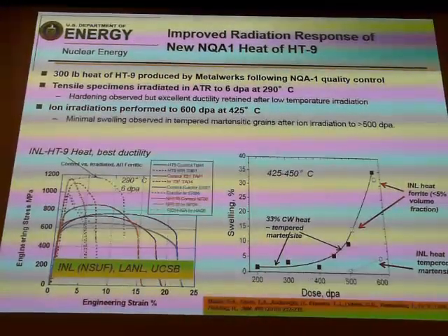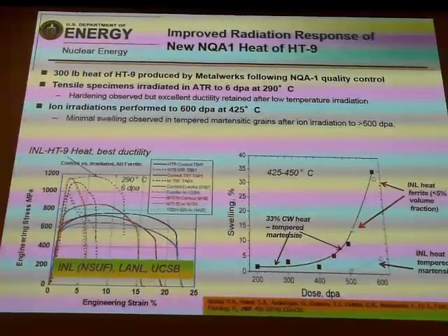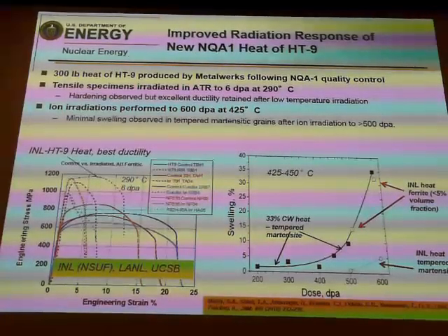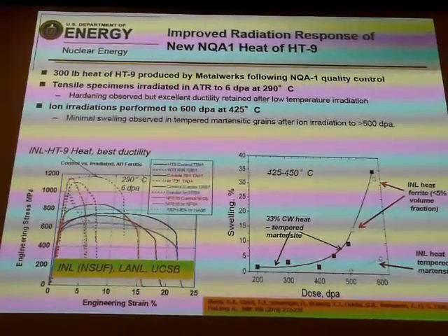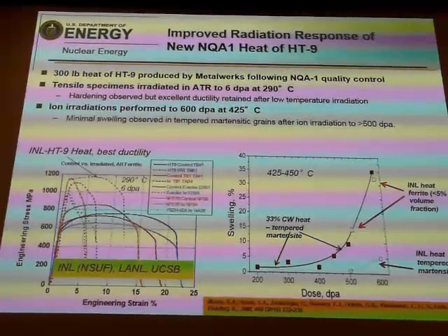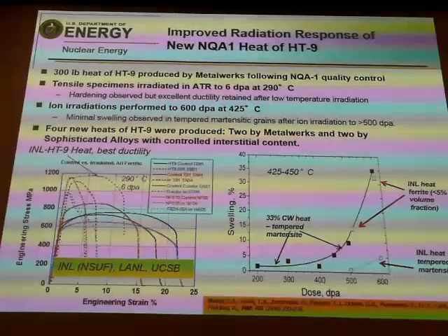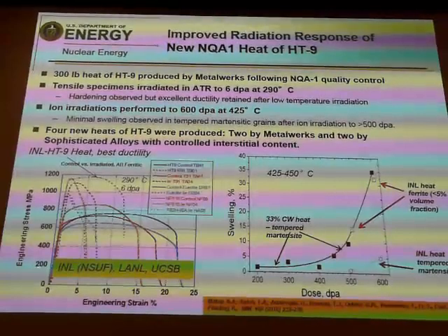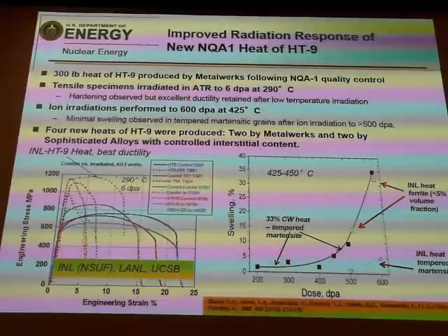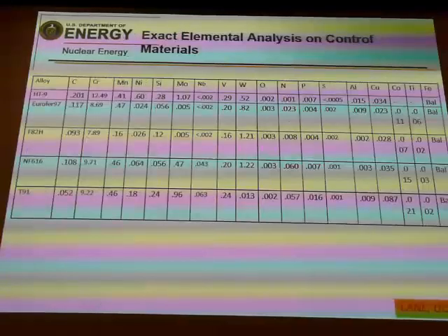With ion irradiations out here to high doses, you could actually see that this material also did fairly well with respect to swelling resistance as well. So we made some new heats of material. We made two by Metalwerks and two by Sophisticated Alloys, and we're controlling the interstitial content in this material.